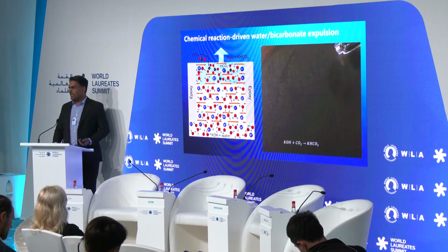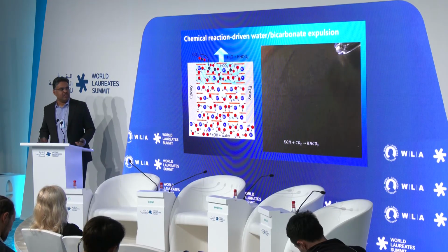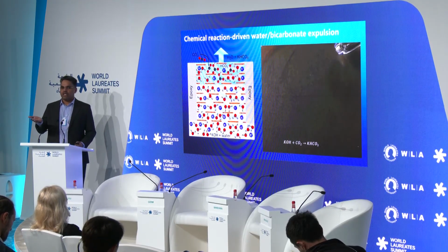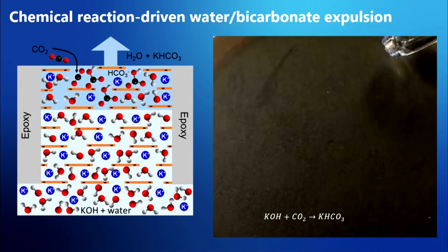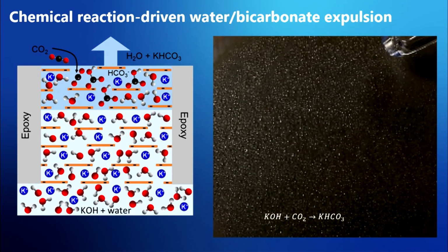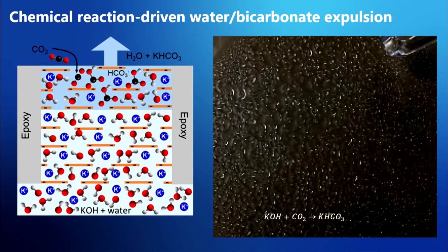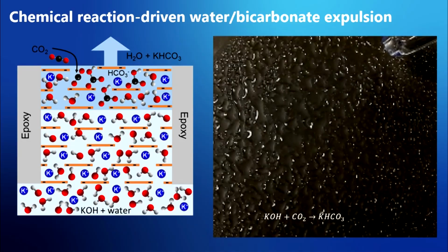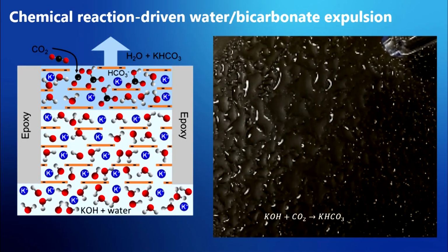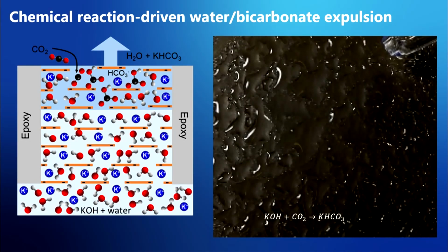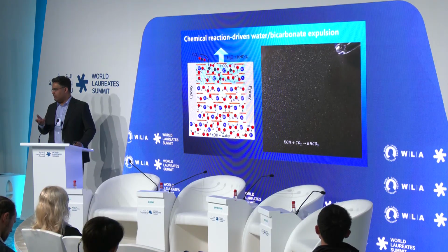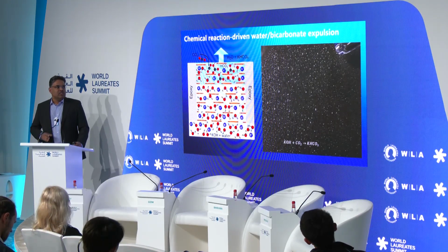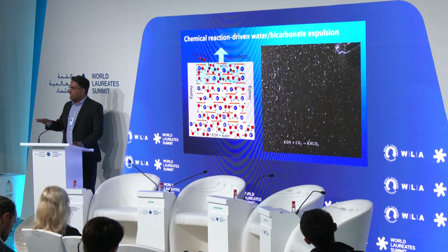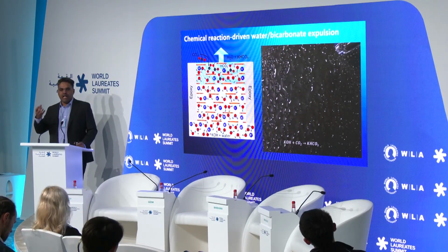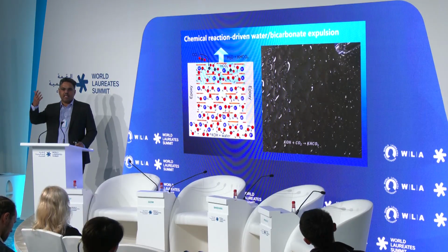So experimentally again we tried, and this is exactly what we see. You take a membrane, put hydroxide only on one side, the other side is air or CO2, and immediately what we see is that liquid water is coming out of the membrane, and you can see big droplets. If you wait for some time, say with a 1 centimeter square membrane, you get tens of milliliters of water after several hours. There is no pressure, there is no external chemical gradient. The only thing is we have alkaline water on one side and the other side is air or CO2.